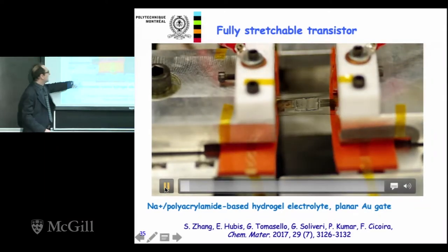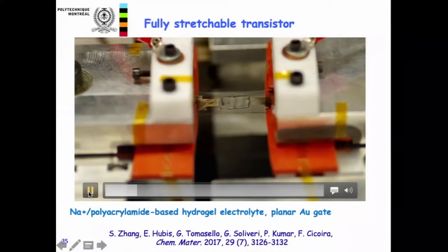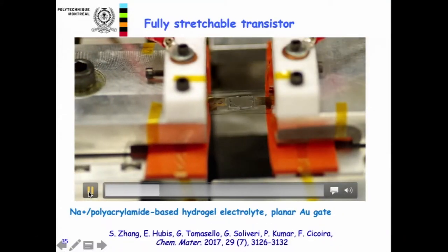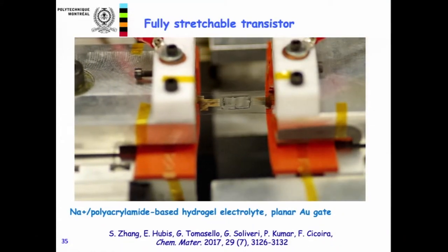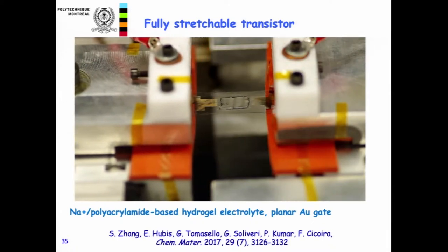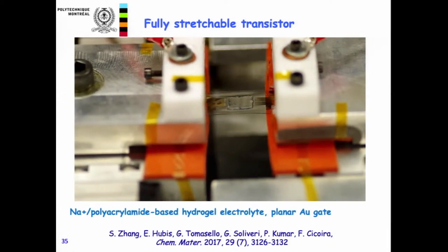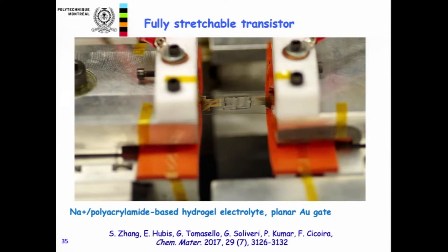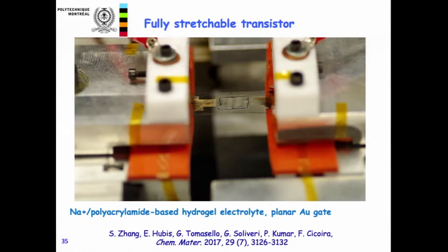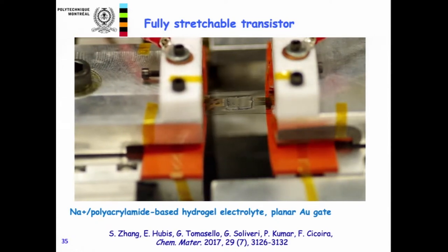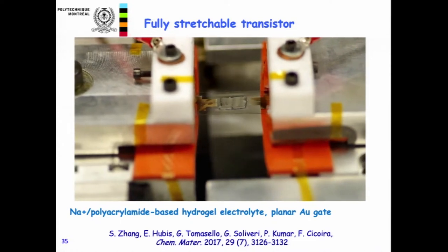This is the way we characterize the device. We have our tensile tester, a homemade tensile tester, connected to the electrical probe station. We make the contacts here to the source and drain. And the gate is also planar here. And you can see here that the acrylamide hydrogel really follows the PDMS. So it's as stretchable as the PDMS, at least.